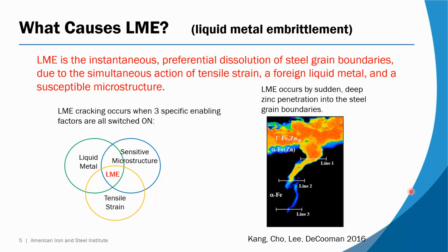The cause of LME is, let's say, the instantaneous preferential dissolution of the grain boundaries in the steel, and it requires 3 things to be present. You need tensile strain, you need a foreign liquid metal such as zinc, or maybe even lead - we don't put lead on steel cars anymore, but we did put it on fuel tanks, so that was my first exposure to it - and a susceptible microstructure.